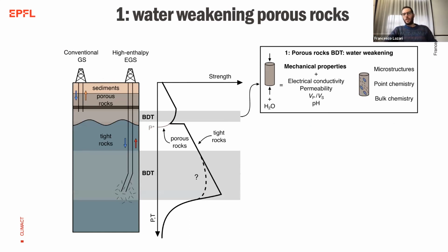First of all, we want to keep studying the effect of the presence of water on the brittle to ductile transition. To do so, we will keep doing deformation experiments at different pressures so that we go across the brittle to ductile transition. We'll do the experiments first without water and then with water, so that we can see what's changing between the 2. And during the experiments, we're going to monitor the electrical conductivity, the permeability, the seismic wave velocity, and also the pH of the fluid that is coming out of the sample to see whether some chemical reactions are taking place in the rock.